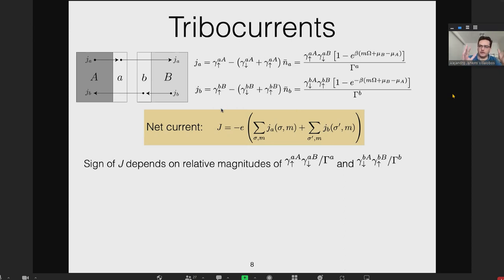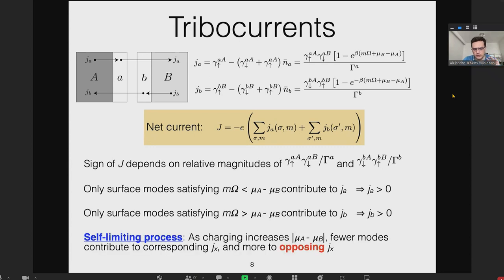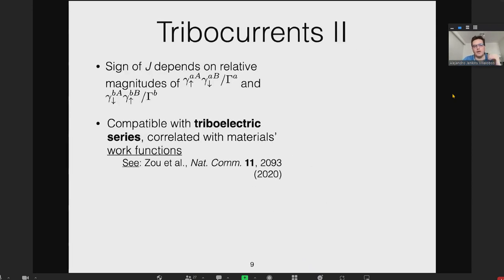If the two materials are equal, the two currents will cancel. But if there's any dissimilarity, one current can predominate. It's very important that this process is self-limiting: if one current predominates so you have net transfer of electrons say from A to B, then the electrochemical potential of B is increasing—it's being charged up. This change in electrochemical potential discourages the current giving the charging and encourages the discharging current, so the process doesn't run away.